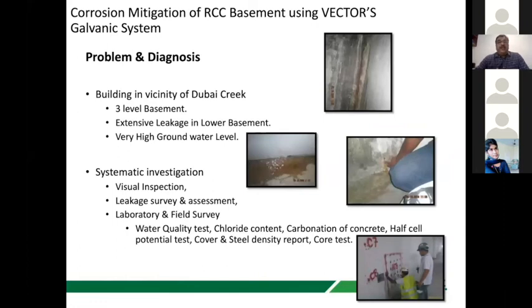So when I visited one of the basements in Dubai, we found that corrosion stains were there and water was leaking. There were no cracks, there was no spalling, but we saw brown rust. So the consultant asked us to do the solution. I said, even if you arrest the water, you won't have a bone dry condition. If it is bone dry, it's wonderful. But as leaking is already there and you are seeing the rust mark, corrosion has initiated and the passivating layer has gone off during the construction time only.